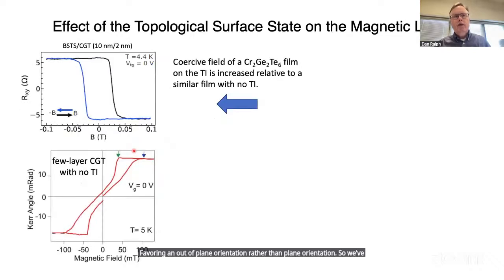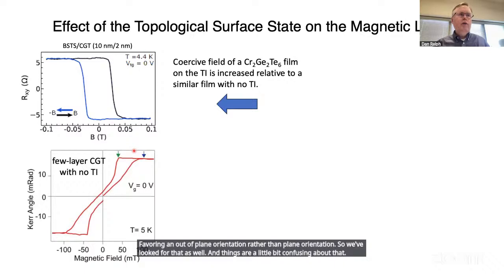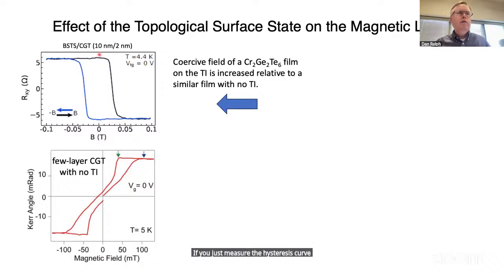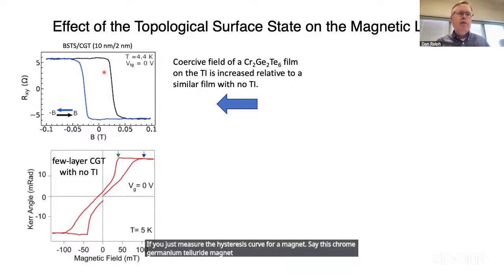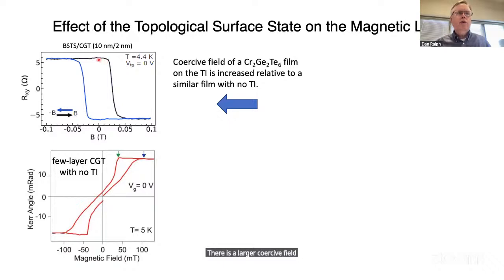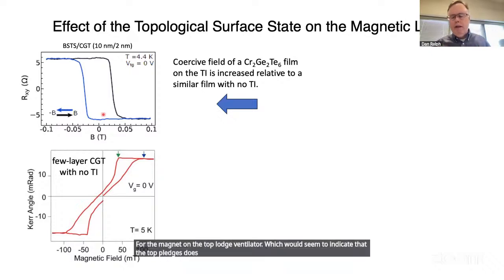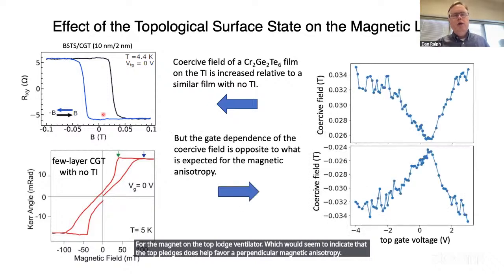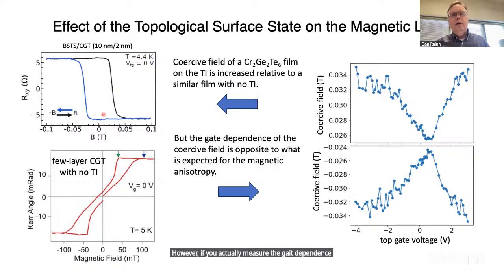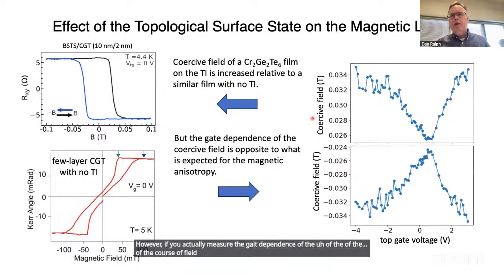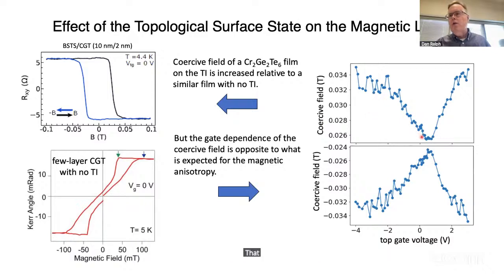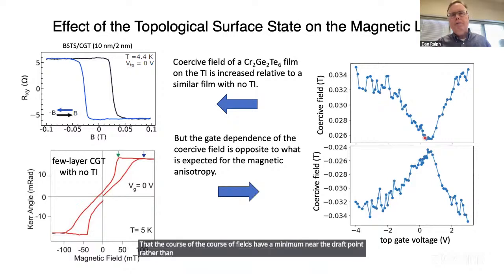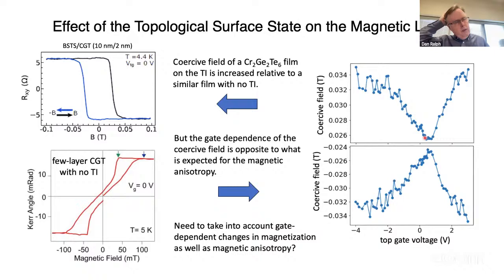So we've looked for that as well, and things are a little bit confusing about that. If you just measure the hysteresis curve for a magnet, say this chrome germanium telluride magnet on the topological insulator versus just on a silicon wafer, there is a larger coercive field and a much more square hysteresis curve for the magnet on the topological insulator, which would seem to indicate that the topological insulator does help favor a perpendicular magnetic anisotropy. However, if you actually measure the gate dependence of the coercive field, you actually see opposite what you expect. That the coercive field has a minimum near the Dirac point rather than a maximum near the Dirac point. So we're still trying to figure out exactly what's going on there.